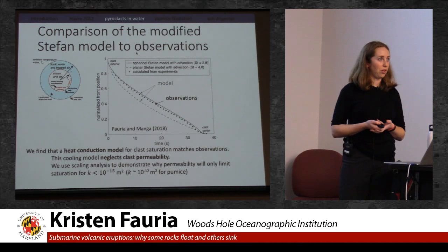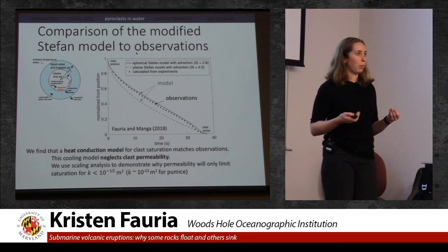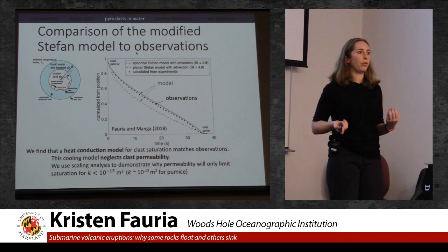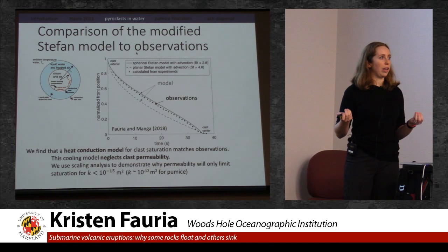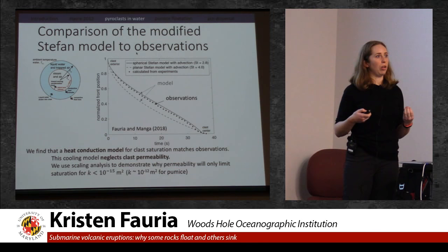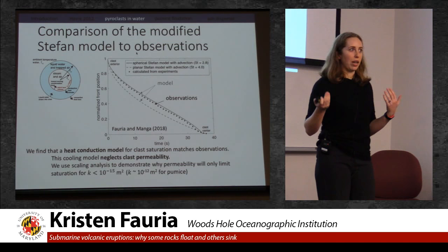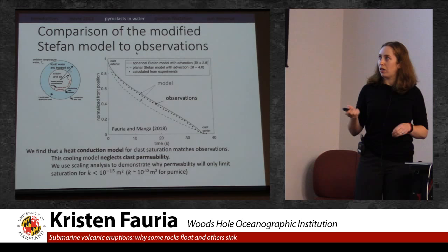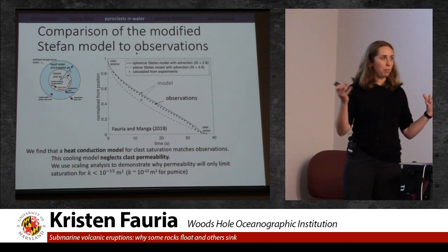This model also importantly neglects permeability, so it doesn't really take into account the resistance of the rock structure to fluid flow. And we used a scaling analysis to demonstrate that you can neglect permeability when permeabilities are large, or above about 10 to the negative 15, which is reasonable in pumice, which has permeabilities that range from 10 to the negative 10 to maybe 10 to the negative 13 meters squared. So we concluded then that cooling controls the saturation of these big porous clasts initially when they're steam filled.